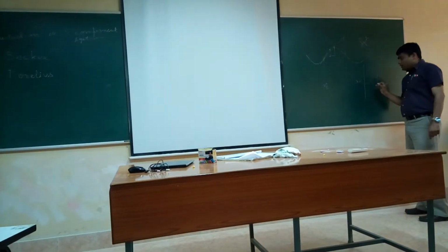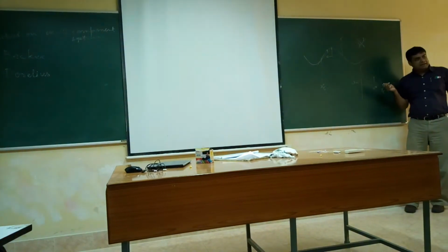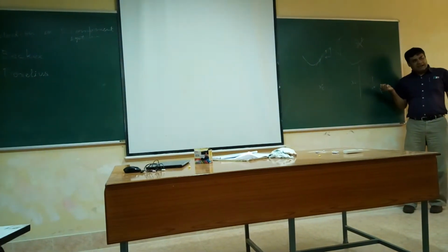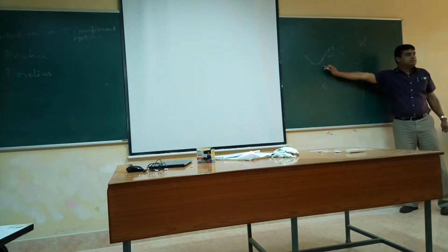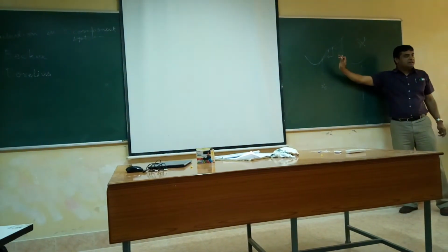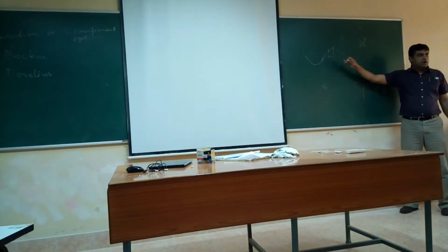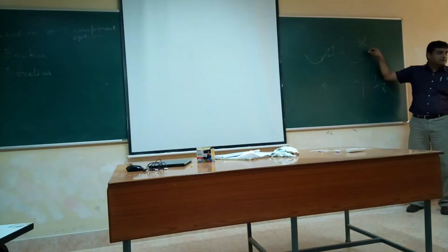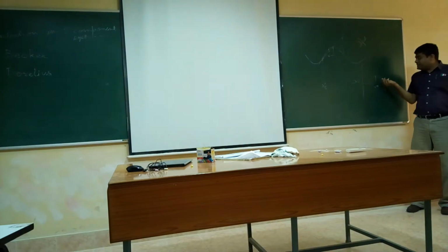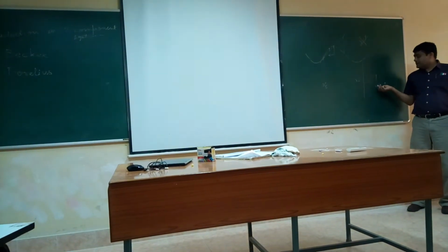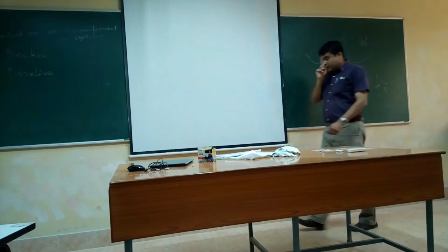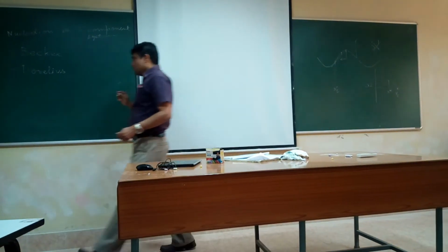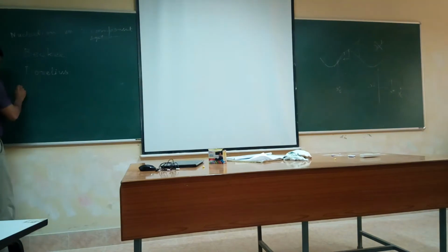So the Borelius model says that a nucleus can be stable even below Xc, whereas the Becker model says it cannot be. Because Borelius ignored this term, it can be stable even below Xc, and above X star it is stable. So those two we talked about.